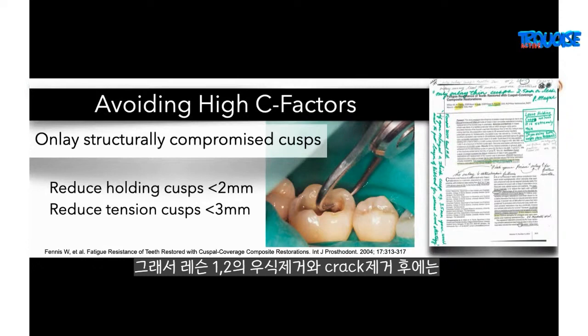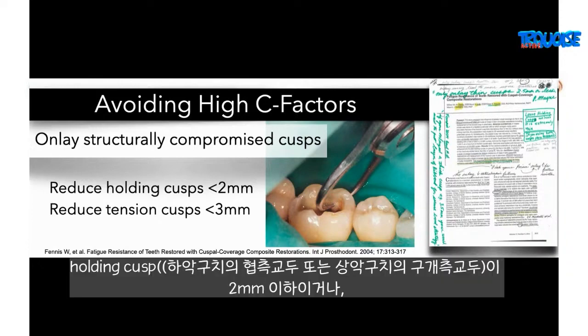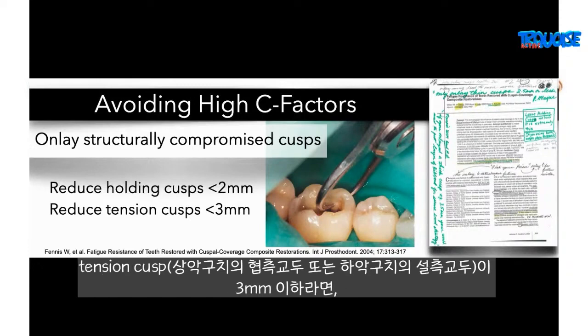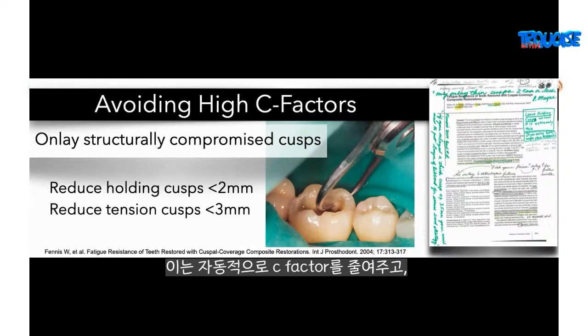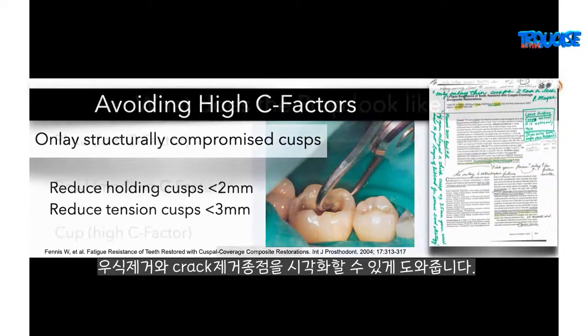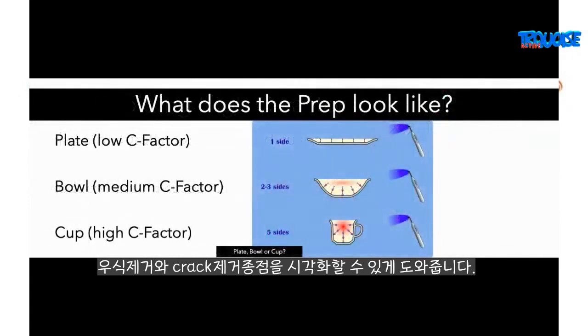And so we always measure the thickness of our cusp after lesson 1 and lesson 2, caries removal and crack removal. And if we have cusps that are less than 2 millimeters, which are the holding cusps, which would be the buccal cusps with the lower molars or lingual cusps with the upper molars, or if we have tension cusps, which would be the buccal cusps of the upper molars or the lingual cusps of the lower molars, we would reduce those. And that automatically reduces the C-factor and helps you to visualize your caries removal and your crack removal endpoints.